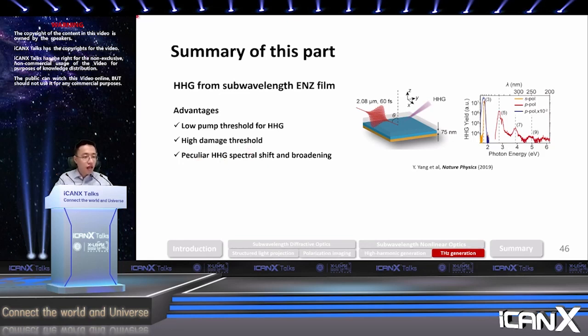And last, we want to look at the outlook. We want to use this structure maybe to create a vacuum UV source with high photon flux, because in this case we can use a pump laser with a very high repetition rate. And we can also potentially use this unique spectral shift and broadening to promote the generation of isolated attosecond pulses.